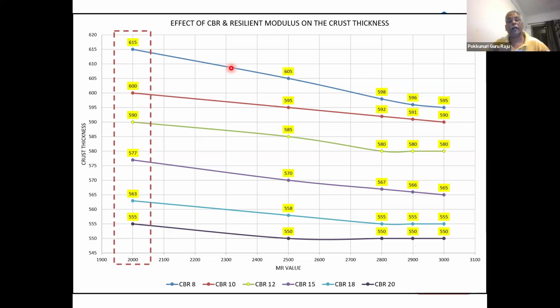Meaning what? When you have a low CBR value, your crust thickness is high. And when you are moving from 2000 MR to 3000 MR, that is 1000 values, if you are changing your MR value by 1000, you are able to reduce your crust thickness from 615 to 595, that means 20 millimeters. So for every 500 MR value, you are able to reduce your asphalt layer thickness by 10 millimeters.